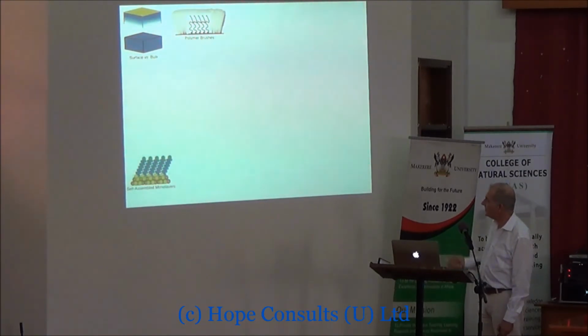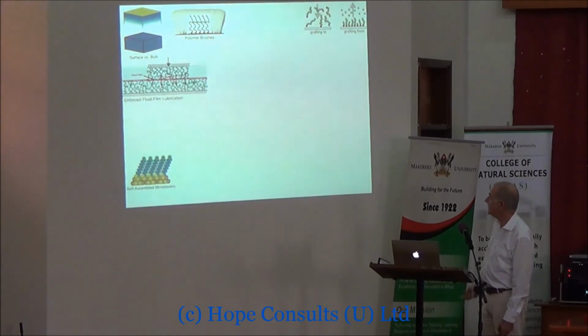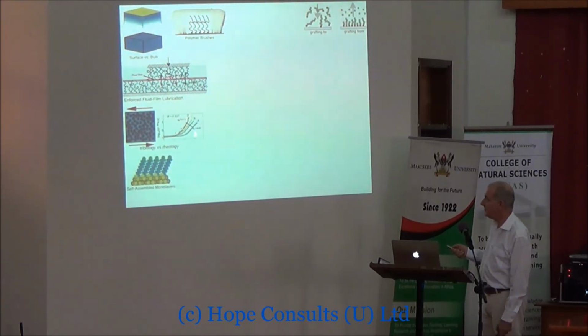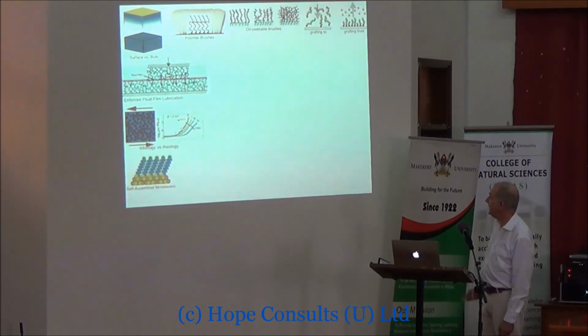Then I talked about polymer brushes and how we can use those to make surfaces lubricious and biocompatible, and the different ways in which we can make polymer brushes, how polymer brushes can lubricate surfaces due to this fluid film that's at the interface of the two polymer brushes, thereby for entropic reasons, and then how we can use polymer brushes to influence rheology by changing the tribological properties of the grains as they slide past each other in cement. I talked about oil-compatible brushes where we have these hydrocarbon side chains and we can make surfaces much more lubricious by having the long polymer chains on the surfaces.